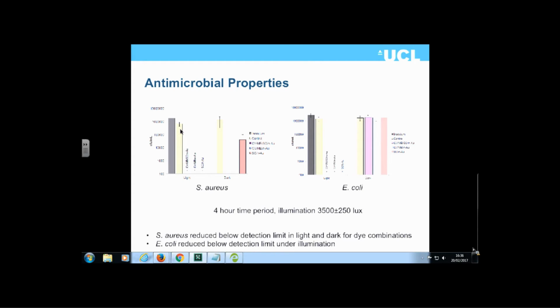So here, the higher the bar, the less bacteria are killed. But with crystal violet, methylene blue and gold nanoparticles plus light, we get virtually complete kill of Staphylococcus aureus. Particularly exciting, we also get complete dark kill for the crystal violet samples—the same antimicrobial properties as the old tincture your mum would put on a grazed knee. It still works the same way in the dark.